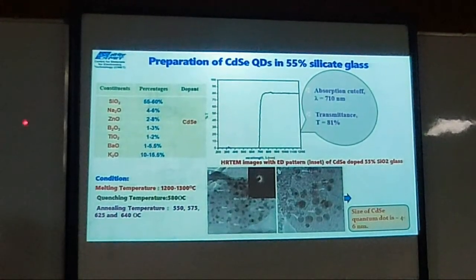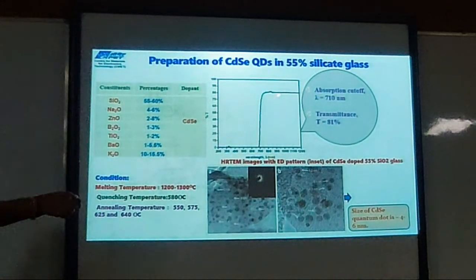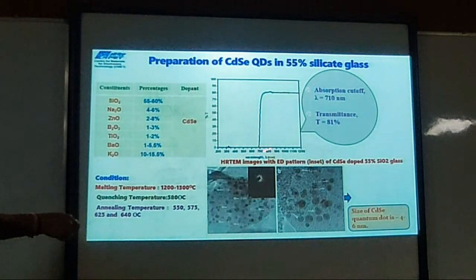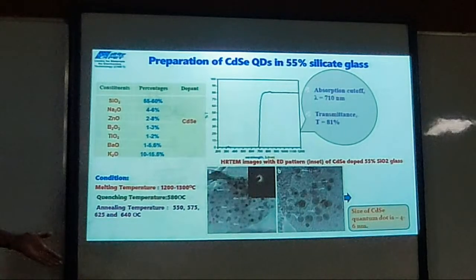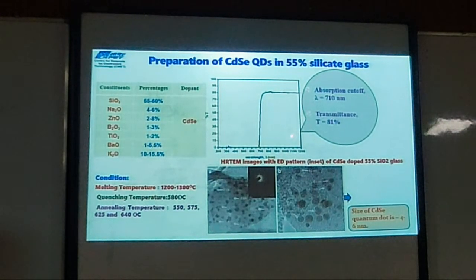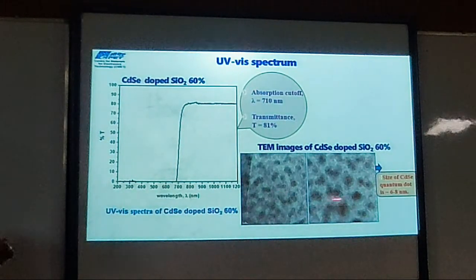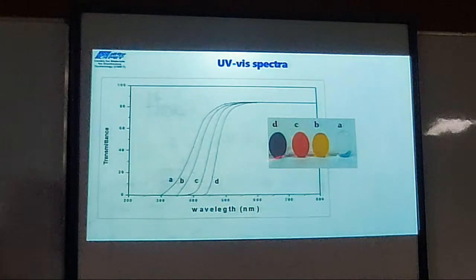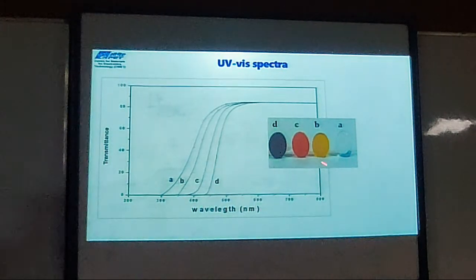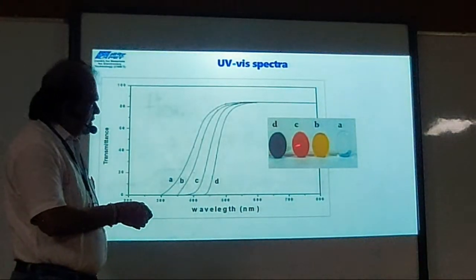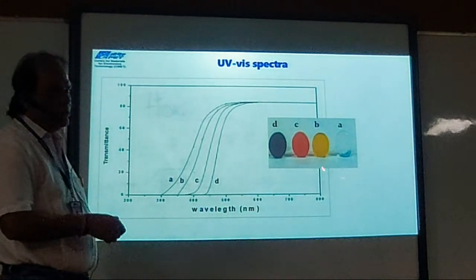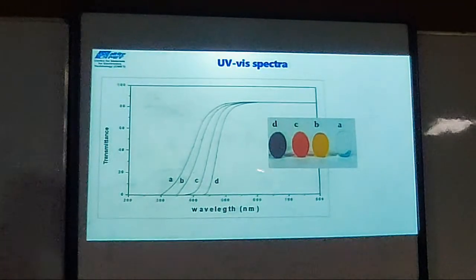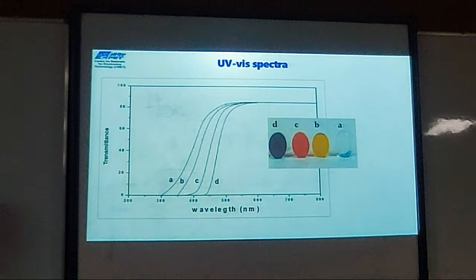So this is CdS, and CdSSe we also developed. They have a cutoff around 710 nanometers, which is almost in the near IR region. So this glass can absorb light from near UV to almost near IR, which will be helpful for our photocatalytic purpose. You will see here 6 to 8 nanometer CdSSe very uniformly dispersed in the glass. And see here, initially it may be colorless, but as you give the heat treatment to the glass, cadmium sulfide or cadmium selenide forms inside the glass and gives this color, meaning their optical properties get changed.